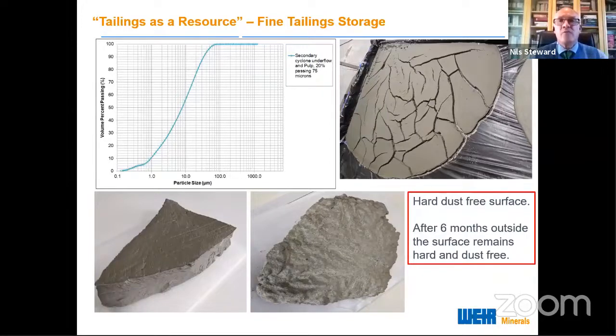If you look at this small portion over here, that portion there is that sample there. We left this outside in Melbourne weather for 6 months, which meant that it saw very low temperatures through winter. It saw very high temperatures as well. It saw a lot of rain. What happened is it did not dissolve. The surface of this product, owing to the very fine particle size distribution, possibly owing to the nature of the flocculation, owing to the way that it desiccated from the surface as opposed to losing its water from the bottom, it has produced this hard, dust-free surface.